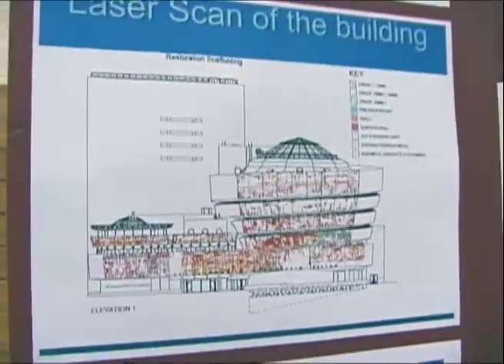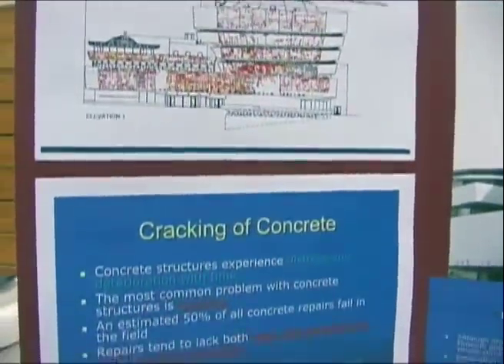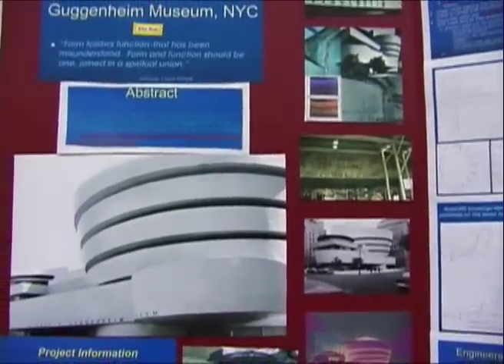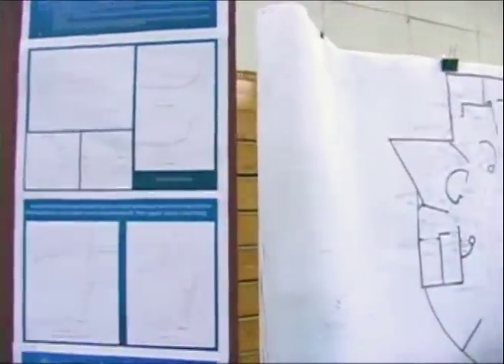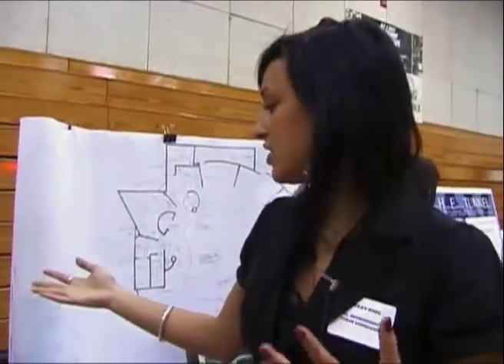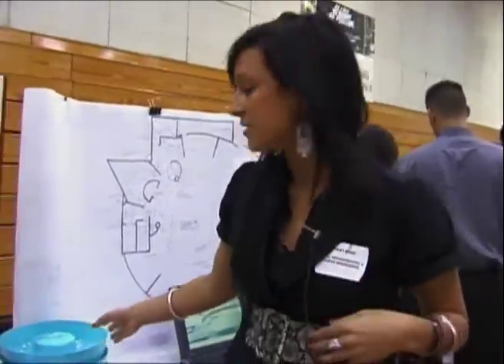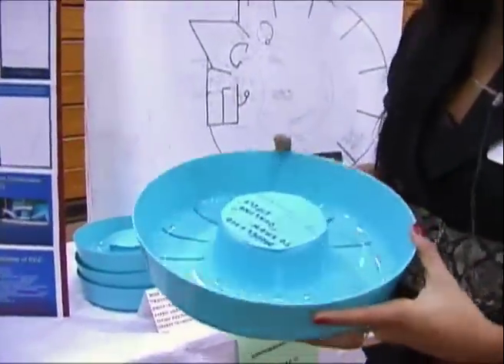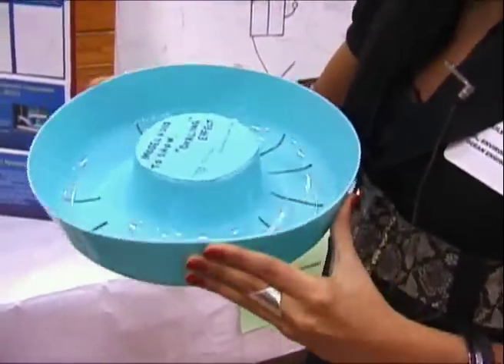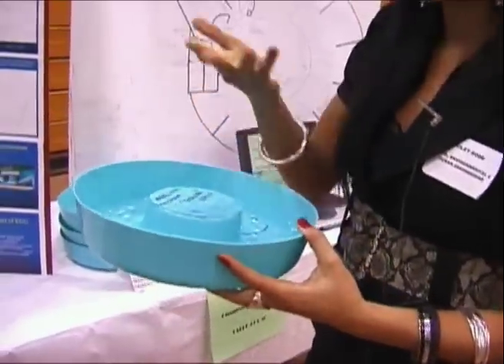My project explored the causes of the cracking, which I deemed to be the temperature differential as a minor cause, but basically the problem of wind loading was the major problem. I studied and made drawings from the original 1959 drawings of Frank Lloyd Wright, obtained through the Paratus Group, which is the museum's representatives. From these drawings I could do wind calculations on the building, and I saw that there wasn't sufficient reinforcement on the cantilevered walls. These are the web walls and these are the cantilevered walls. When the wind hits a building, it causes an ovaling effect, and with the ovaling, the cantilevered walls become deflected, which causes stresses in the concrete, which essentially cracks the building.